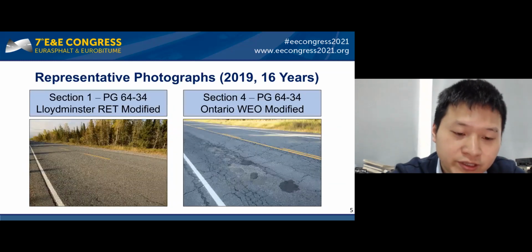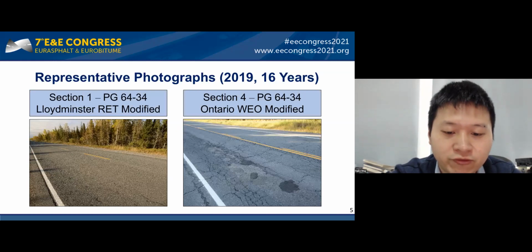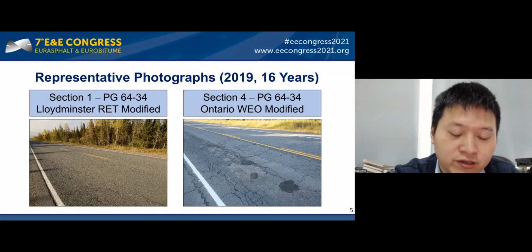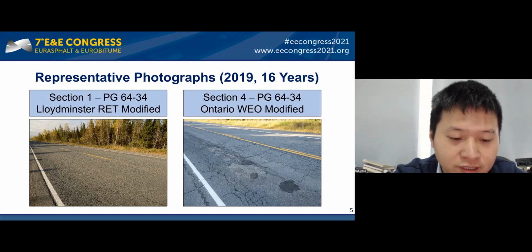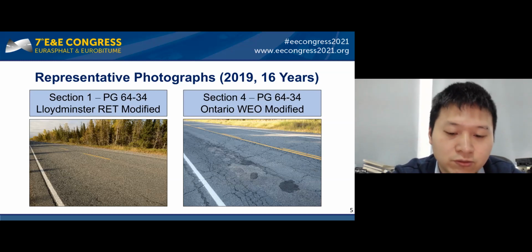Here are two representative photographs of the best and worst performing sections after 16 years of service. It is obvious that the Lloydminster asphalt modified with a small amount of RET polymer performs very well, and that the the binder modified with waste engine oil residue from Ontario has not done too well. This is not a good result for the Superpave specification, as both binders were supposed to provide similar performance, whereas in fact they perform on opposite sides of the spectrum.